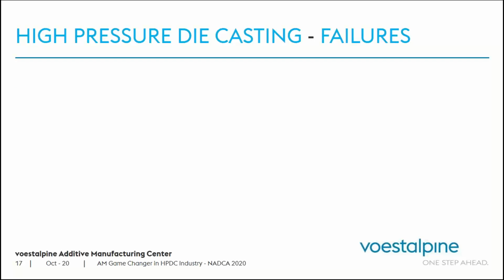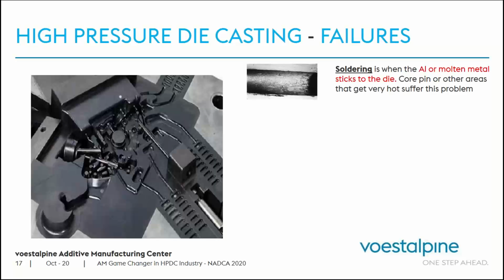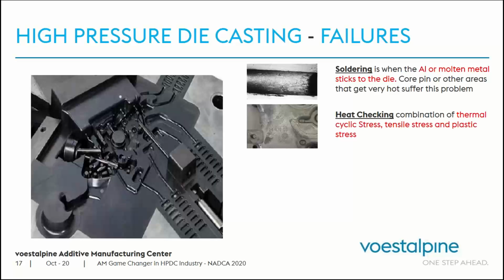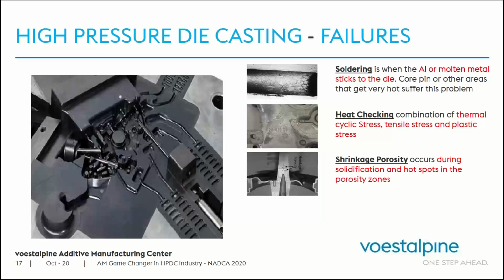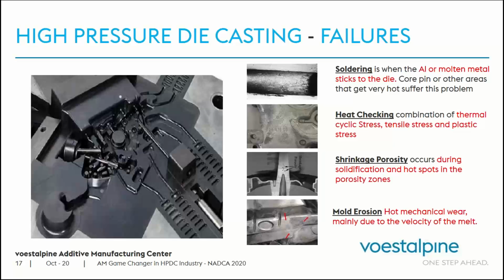If you look at high pressure die casting, what are the common failures? Common failures are like soldering, which is when aluminum or molten metal sticks to the die. This is one of the common problems. Another problem is heat checking, which is a combination of thermal cyclic stress, tensile stress, and plastic stress. Another failure is shrinkage porosity, which occurs during solidification and hot spots in the porosity zone. And another common failure is mold erosion, which is a hot mechanical wear mainly due to the velocity of the melt. So these are common failures that happen with the traditional mold being built.